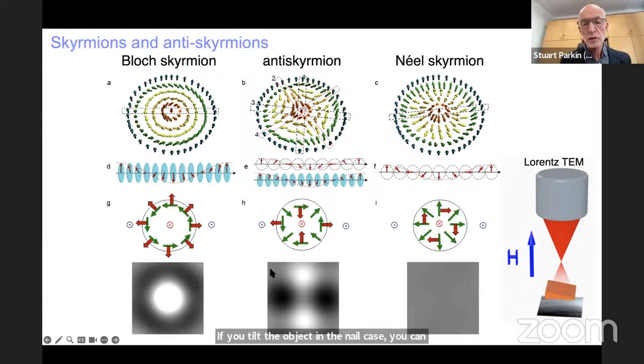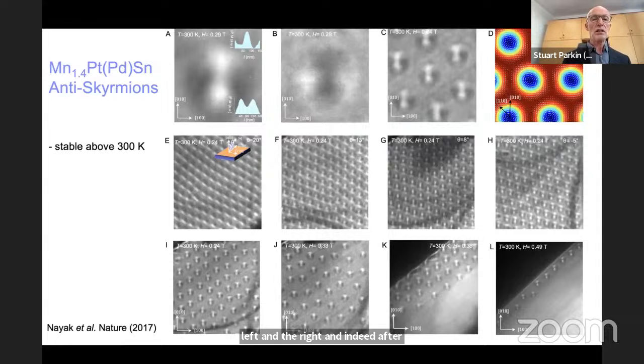And in the antiskyrmion, we calculated we should see this clover leaf-like structure with two regions of increased intensity shown to the top and bottom, and two regions of decreased electron intensity to the left and the right. And indeed, after considerable efforts, we could see this. This is work originally by Ajay Nayak, who was a postdoc in my group. And these are some beautiful single crystals of this material.